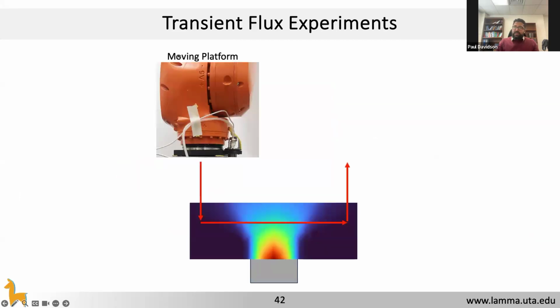Then we are also doing moving platform tests. That means we take the material and pass it through the flux profile at different velocities, and then characterize the material itself for both crystallinity as well as distribution of crystallinity through the thickness of the tape, and see how the flux profile and the velocities influence that.